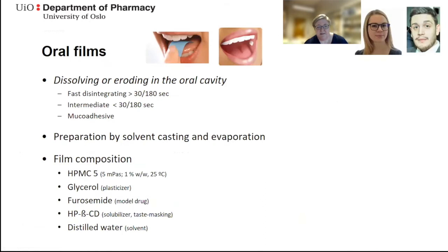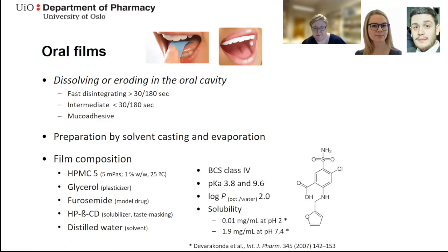So I thought I should present some results from our research on oral films. We have looked at both disintegrating and more mucoadhesive systems. We will start out by looking at some very simple HPMC based films that were prepared by solvent casting and evaporation. And we used furosemide as the model drug.